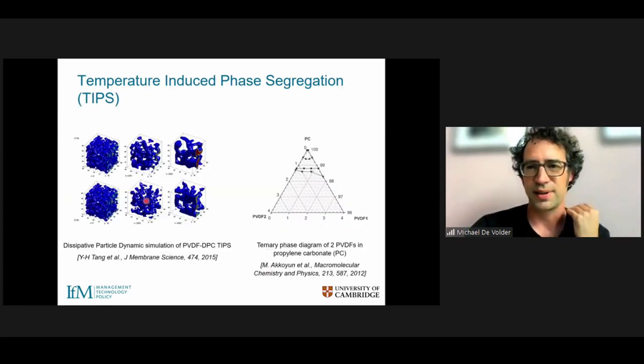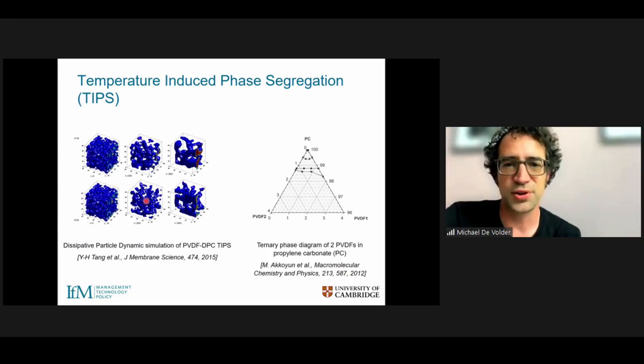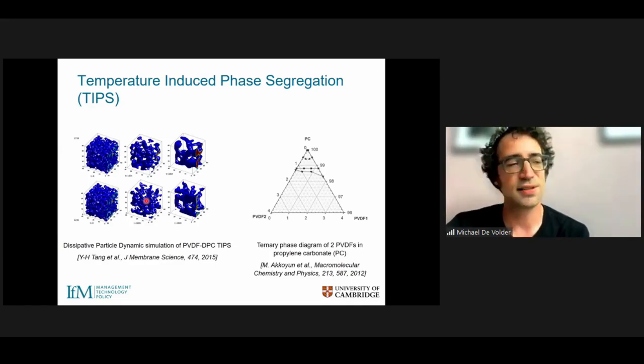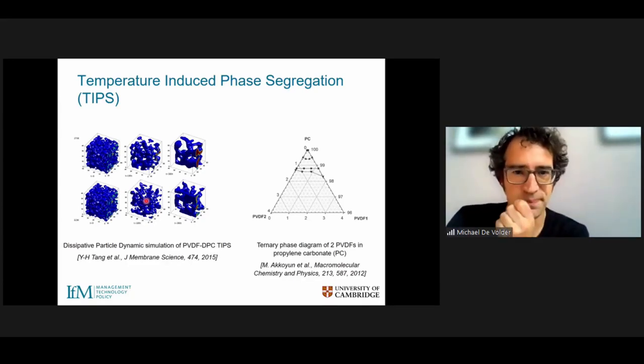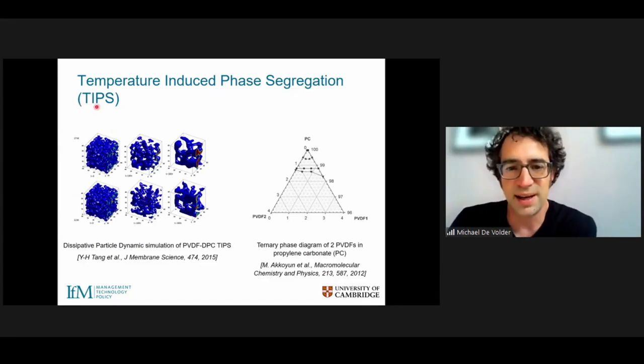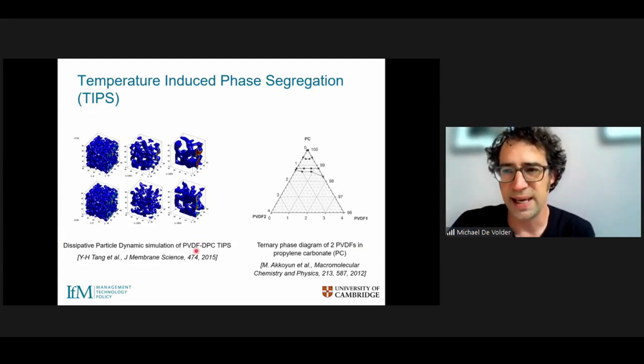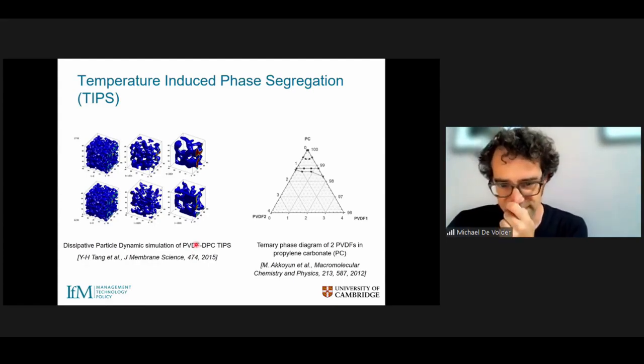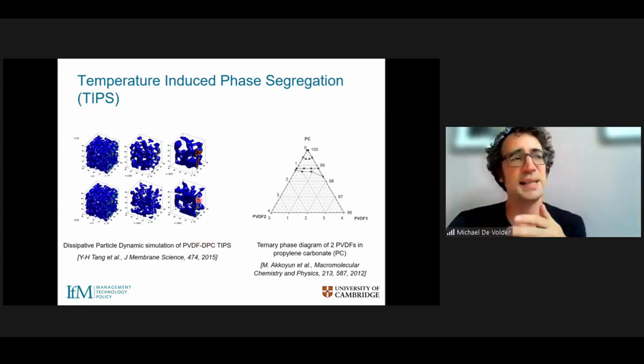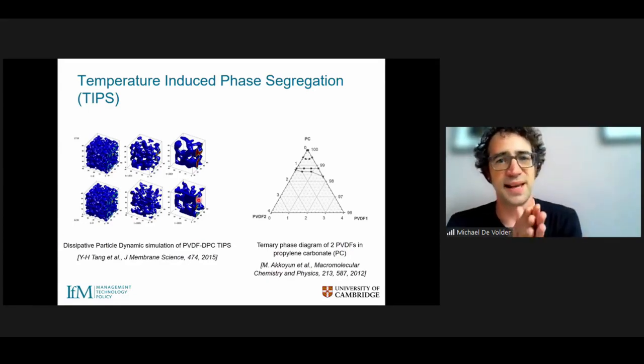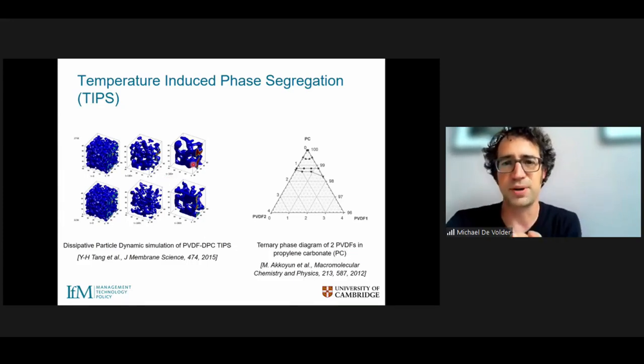And so when I started working on these thick electrode concepts, the postdoctoral researcher who was working with me, Dr. Jung-Tae Lee, had some background in polymer processing and in particular in phase segregation processes. And so what you are seeing here is some work from literature where people studied temperature-induced phase segregation, a process called TIPS in short, of a particular polymer, in this case PVDF, which is a fluorinated polymer. And what these simulations show is how if you dissolve PVDF in certain solvents, it will typically disperse well at high temperatures, but when you cool down the process and arrest it, it can form bicontinuous networks of, on the one hand, the polymer that crashed out of suspension at low temperatures, on the other, the rest of the phase would be the solvent.